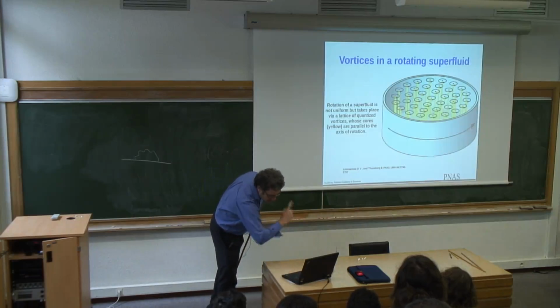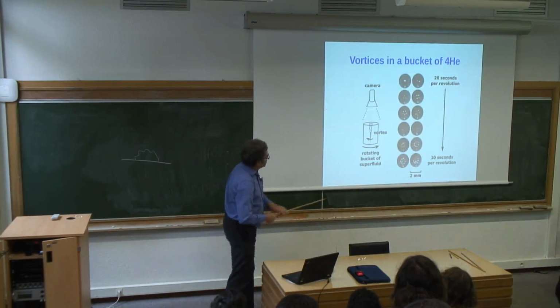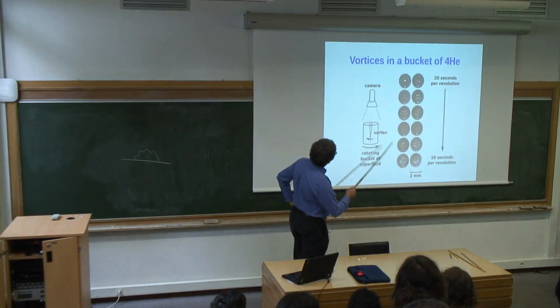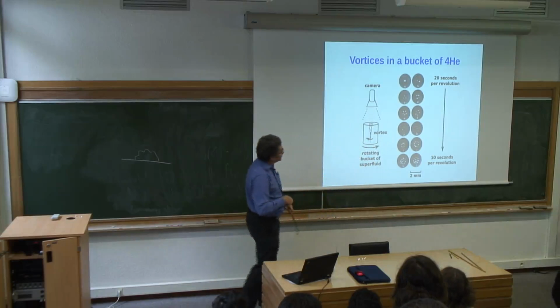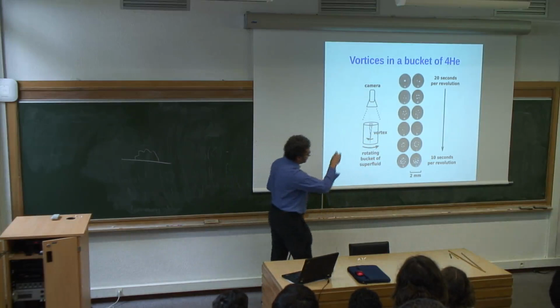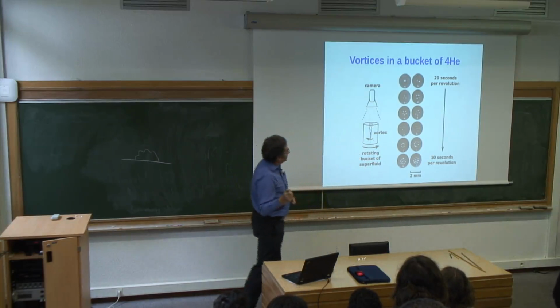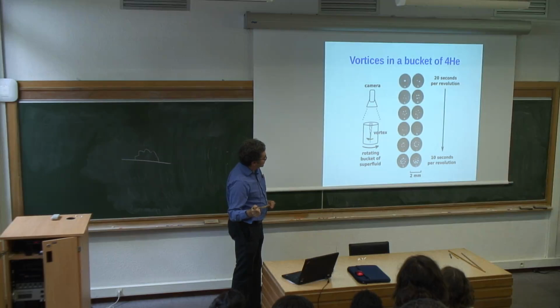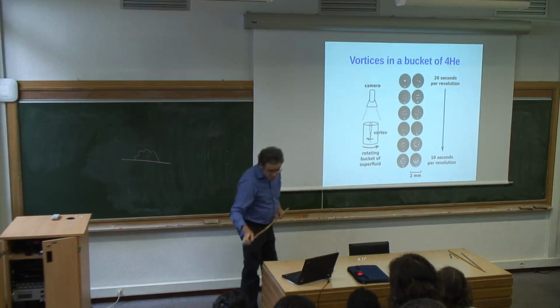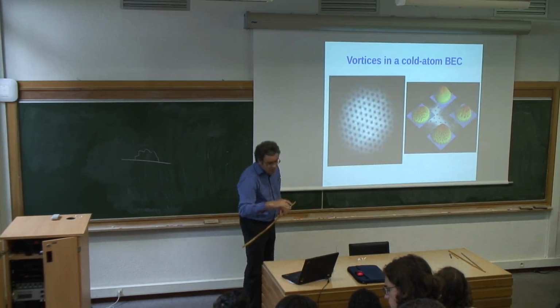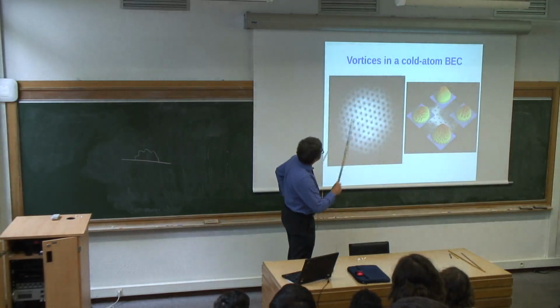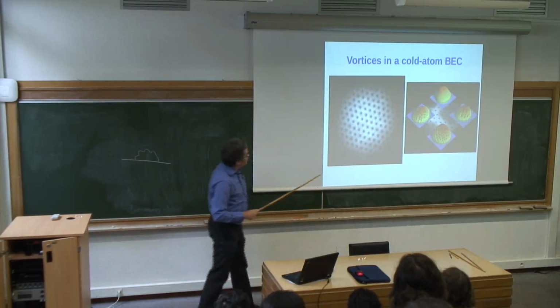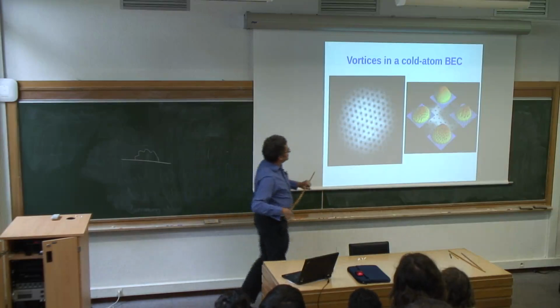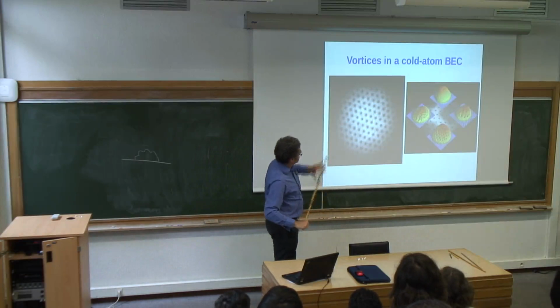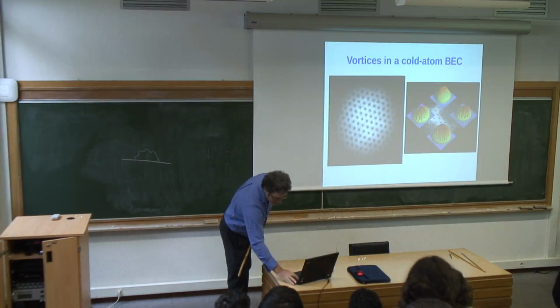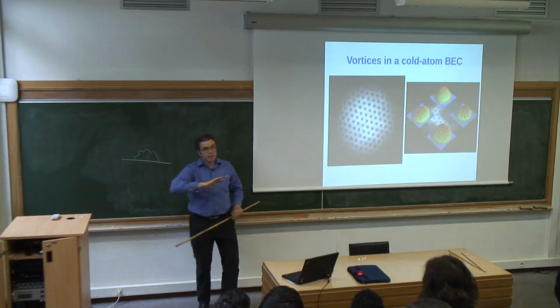Right. And so this was an artist's image, but this is actually data from that same paper, where they take a bucket of superfluid helium and spin it faster and faster, and then image vortices that appear in the bucket as they increase the revolution speed. And these are pictures from experiments on cold atom BEC, where people have time-of-flight techniques for imaging vortices, but from the symmetry point of view, it's the same story. Okay, so that's symmetry.